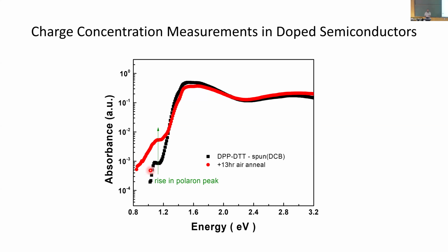This is a polymeric sample, a p-type polymer which has been doped, and we can precisely see the absorption from the doped state. If you know the absorption cross section, you can measure the quantity of doping in your material. This is one use case, it just tells you how much doping is there. You can of course reconfirm the same using a device result, that's also possible, but this is the easiest thing because you're just making a film, not a device.